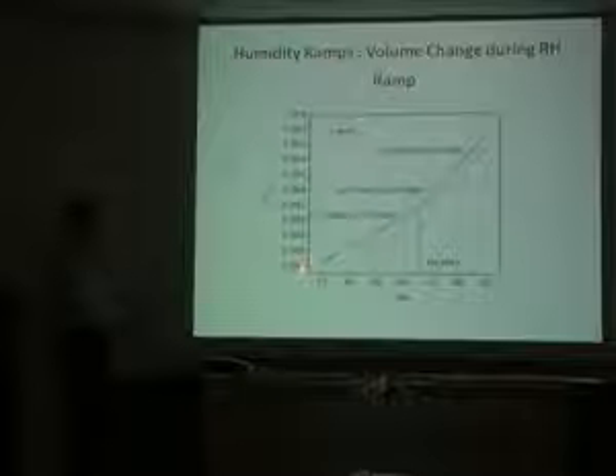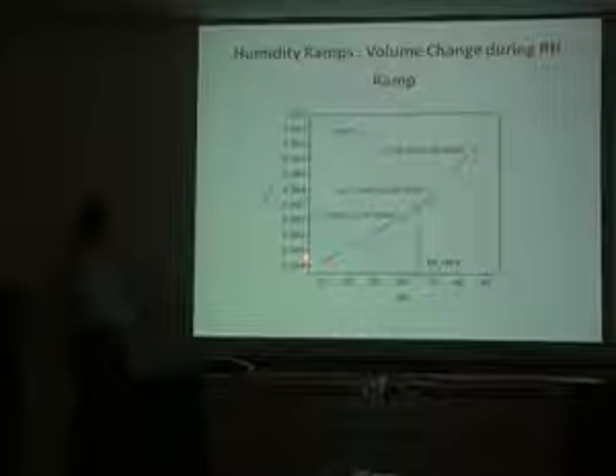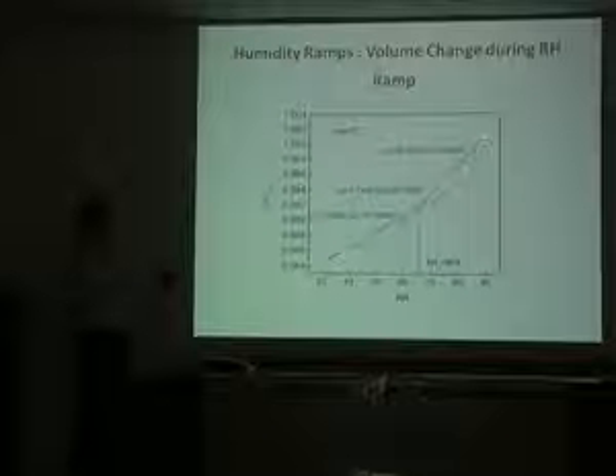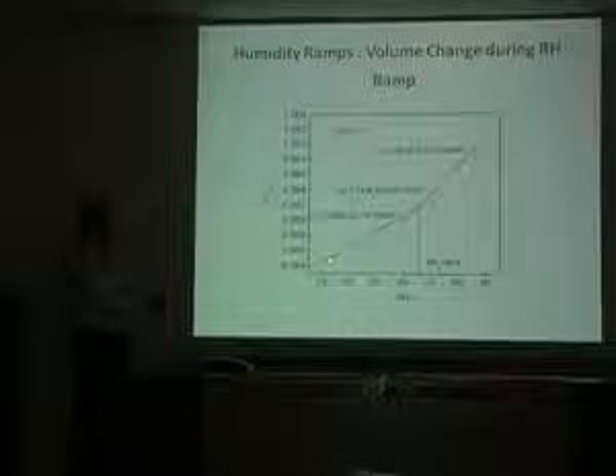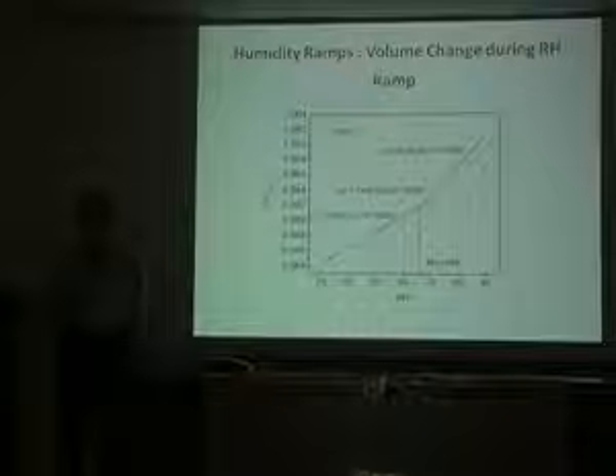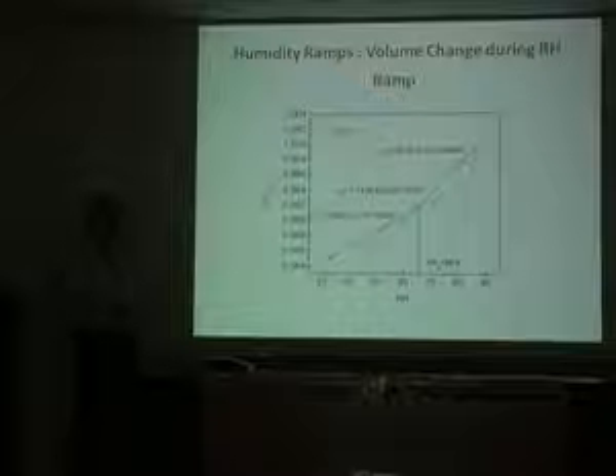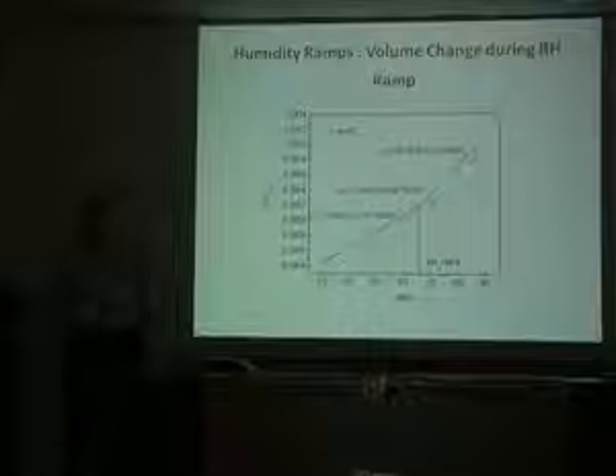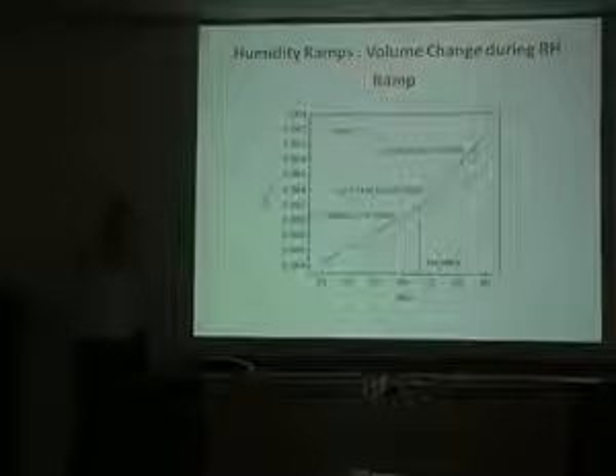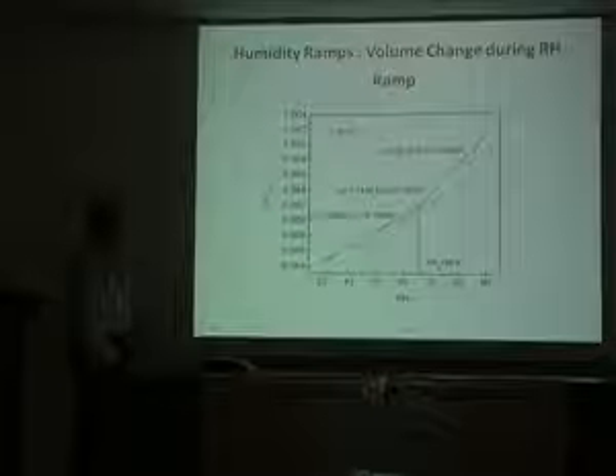And here's an example of a volume normalized to some reference volume as a function of relative humidity now as we dehumidify the sample. And we get an alpha, which is now related to relative humidity instead of temperature, for example. And we would have a delta alpha related to relative humidity instead of temperature. And we have a relative humidity glass transition of about 66% under these conditions, which were something like 2% change of relative humidity per minute.